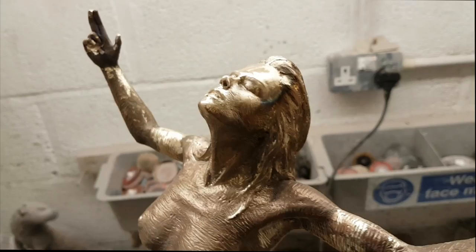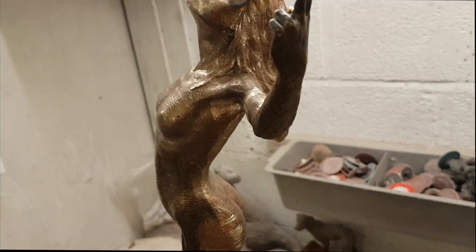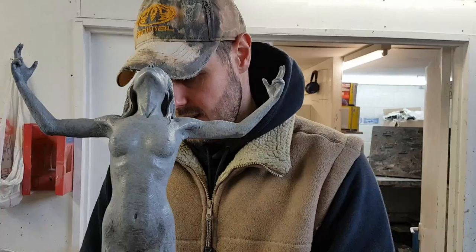What's happened here is the sculpture had porous parts in the bronze — in the nose and in the forehead — some holes and pits. So what I've done is I've welded that up. That's what created the large lump. And then I've fettled it back in using cutting tools to cut the shape of the nose. So I've re-sculpted the nose in bronze.